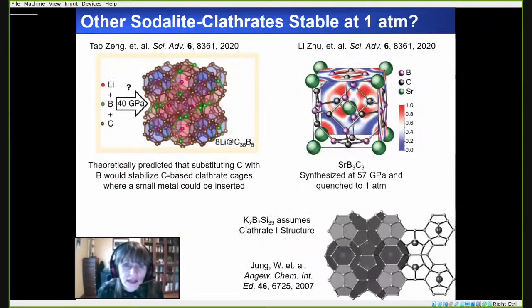Now I would like to talk about other types of superconducting species, in this case ones that could be quenched to 1 atmosphere, because these hydrogenic cages that I have just shown you will most likely fall apart after the pressure is released, because the hydrogen-hydrogen bond is just not going to be that strong in these three-dimensional clathrate-like lattices. So there are no pure carbon clathrate lattices that are known.